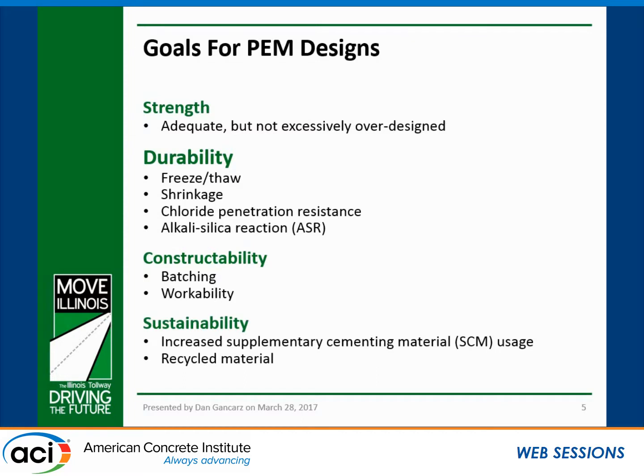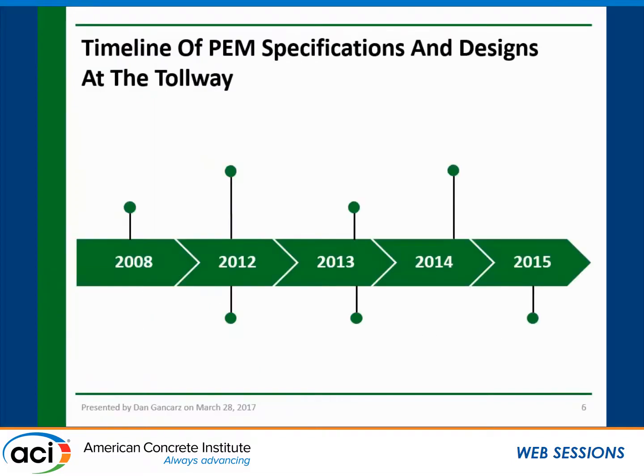And then finally, sustainability. The Tollway has a big emphasis on sustainability, so we're looking for ways to increase SCM usage and then also incorporate recycled materials when applicable. So here's a timeline of performance spec implementation at the Tollway. It started back in 2008 with accelerated weekend patching mixes. These are Portland-based systems that typically achieve 2,500 PSI in 16 to 24 hours. So not high early strength, but they are accelerated.